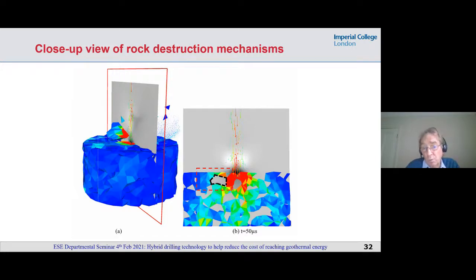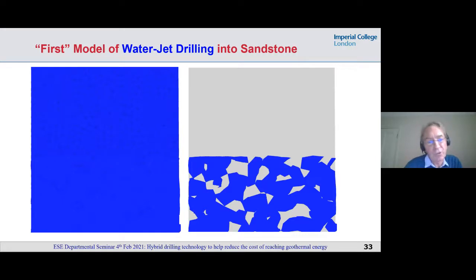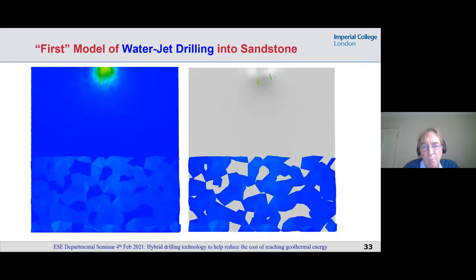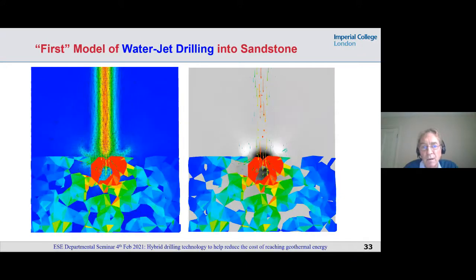Our model will capture the fluid flow both above with those turbulent jets coming in and the pore fluid flow inside the granular system itself. So I want to show you that. The left-hand figure shows you the meshed fluid domain, and you can probably just make out the fluid domains inside the granular quartz sandstone. On the right-hand side, this is much clearer. You can see the pressure field in grayscale and what's happening to those solids. And they're going to be shattered and start moving away as we now bring in that 300 meters per second right in the middle of that jet.